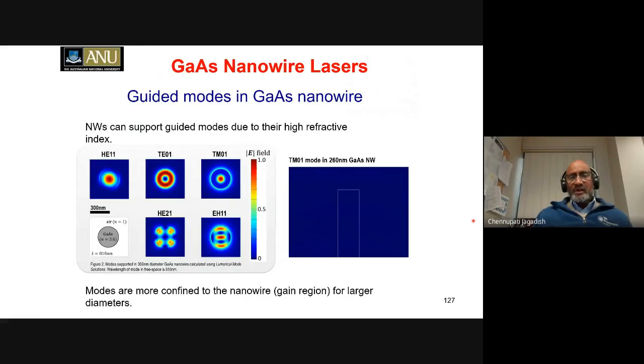And here's a case where Drew Saxena has been doing FDTD simulations, finite difference time domain simulations, of electromagnetic simulations, essentially how the light propagates through these nanowires, and then how the various optical modes are propagating through these nanowires, for example. Here's an example of the TM01 mode, which is propagating within a 260 nanometer gallium arsenide nanowire. And you can see the field intensity is the highest at the core of this particular nanowire, for example.